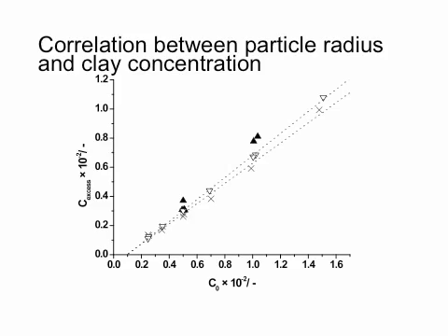And the dots that deviate from this, you see 2 black triangles here, and they're not on this line. So you could say, well, Stefan, you're talking nonsense, because not everything lies on this line. But if you put in the particle numbers there, we use so much clay that the droplet size should be so small that we have a geometry conflict. The droplet should then become about 100 or 50 nanometer, whereas my clay is already 25. So it doesn't fit nicely, we get some geometry issues, and then you start to deviate.